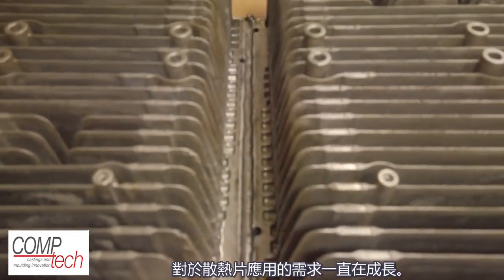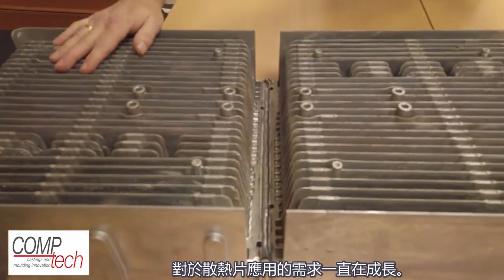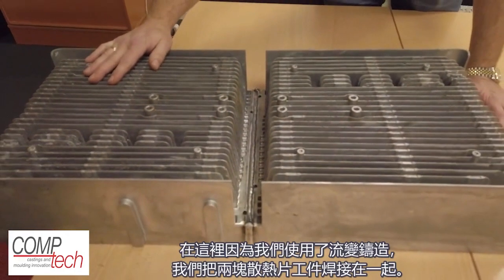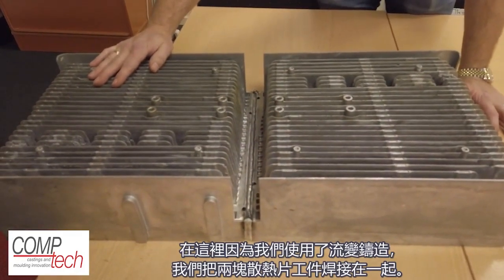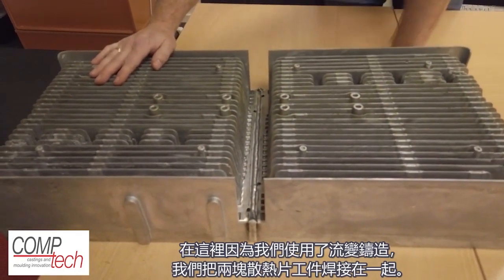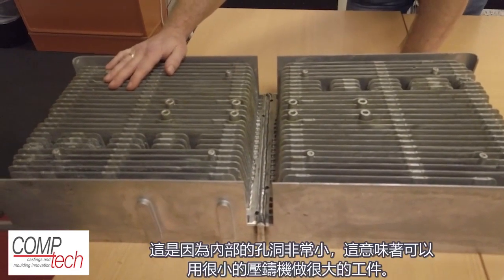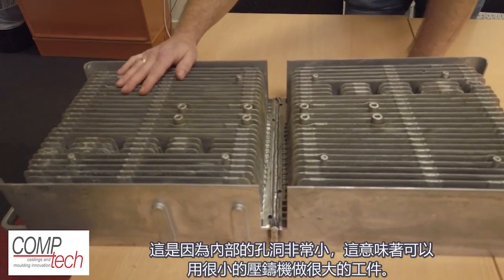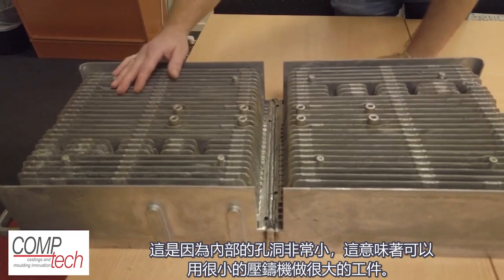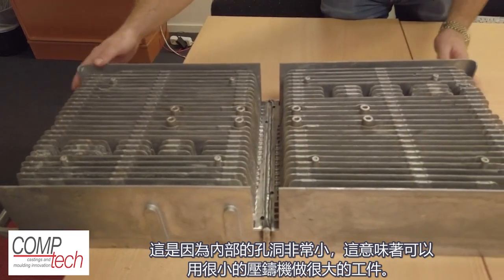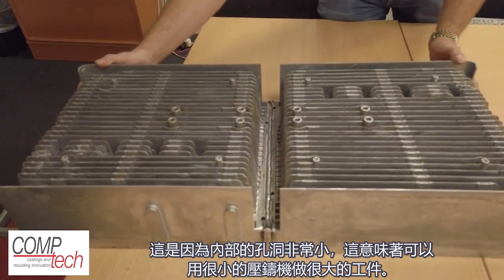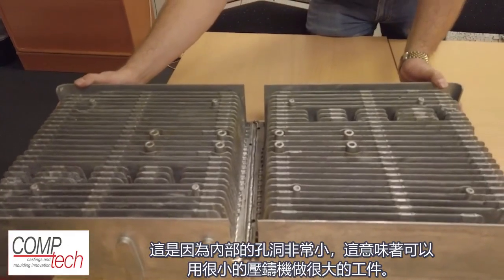The requirement for heat sinks are that they are growing and growing as well. Here we are able, due to Rheocasting, to weld 2 heat sinks together. And this is due to the low microporosity content inside the material, which enables to make a very large casting in a very small machine.